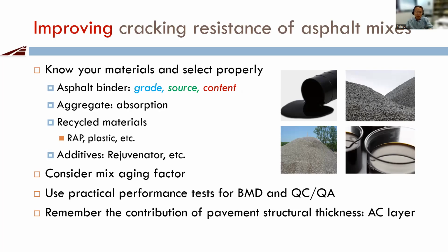So again, to summarize, to improve crack resistance you have to know your materials and select them properly. When you select the binder, look at the grade, the binder source, and the content. Look at aggregate absorption. That's very important. When you're using recycled material, you need to characterize your RAP. Not all the RAP is the same. Not all plastic is the same. When you choose additives, again, do your homework. Not all the rejuvenators are the same. Consider mix aging factors. If your mix ages quickly, you need to look at not just short-term aging, but long-term aging. Use practical performance tests for your balanced mix design and also for quality control during production.